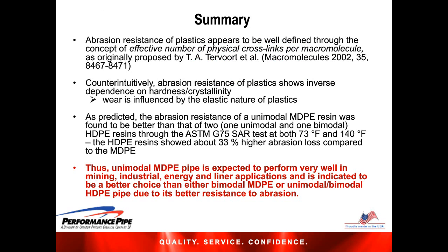So in summary, I think we feel pretty good about the data that we have generated, which appears to show, as much of the literature that I covered showed, that the abrasion resistance of plastics seems to be pretty well defined through the concept of this effective number of physical crosslinks per macromolecule, as originally proposed by Tervoort and his group. It's a little counterintuitive, but it's interesting to note that the abrasion resistance of plastics does in fact show an inverse dependence on hardness or crystallinity, and the wear is influenced by the elastic nature of the plastic. As predicted from the fundamentals, the medium density resin indeed was predicted to show better abrasion performance compared to the two high density resins, and the data in fact proved that out quite well.